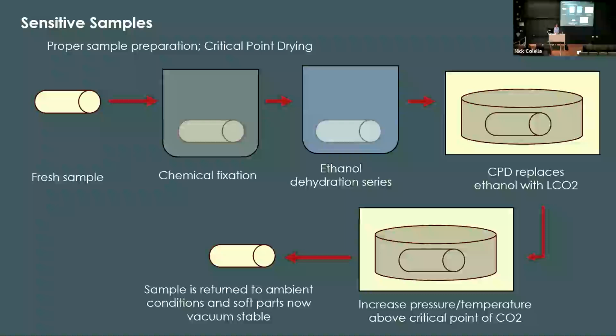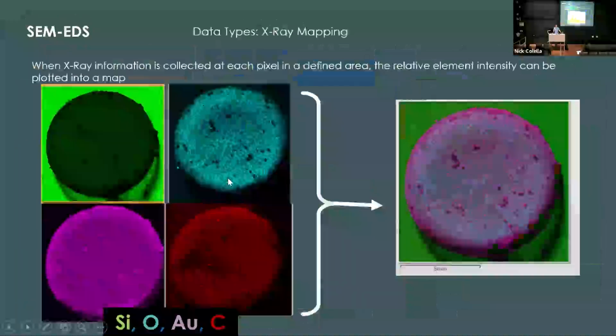Cool. So some facilities will deal with this by having multiple spectrometers, right? From different angles, so that you're capturing the signal from different angles and minimizing the shadowing that way. We don't really have any system set up like that. It makes sense that you will have more trouble with the light elements because that signal is more surface sensitive. That topography is going to be highlighted. That's a tough one. I was going to suggest that our new fancy detector that I mentioned